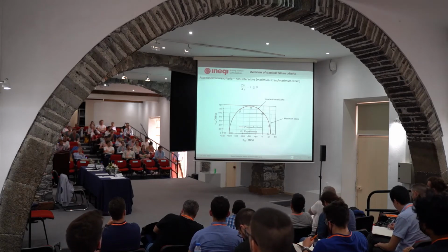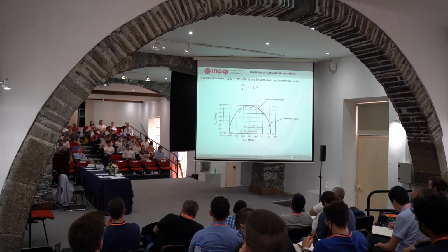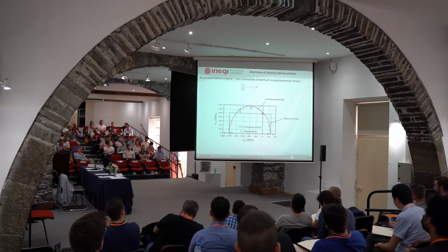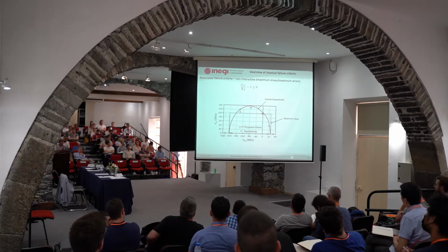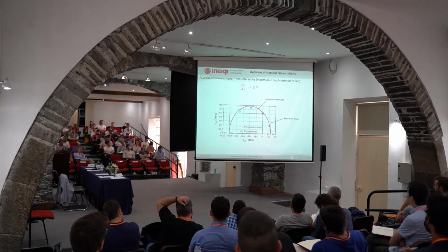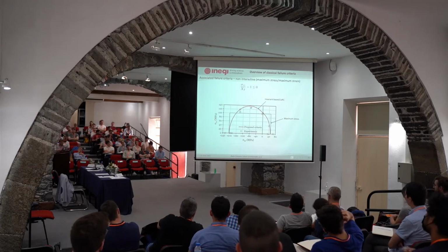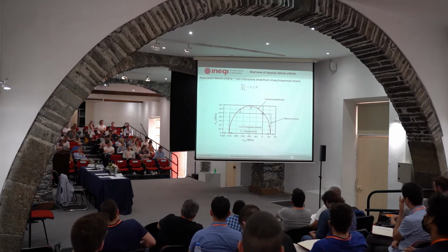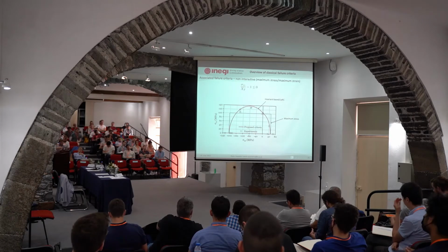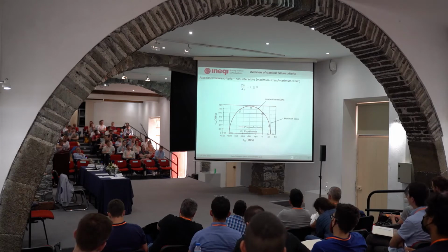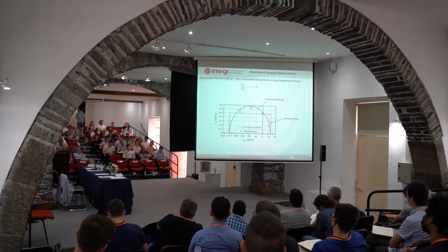Oh, okay, so this is one of the pitfalls. Okay, in this case, this is a non-associated failure criteria. It's maximum stress or maximum strain, and what you can see here, we have some test data there, these circles, and in red, this is what we call the linear or invariant failure criteria. You can capture this effect that you can see here, which is important. You see, this is the shear strength of a ply, right? So if you have moderate values of the transverse compression, this value of the shear at failure increases, okay? And of course, maximum stress is not able to capture this effect here. So maximum stress, there are regions where it's not conservative, and there are regions where it's too conservative, okay?